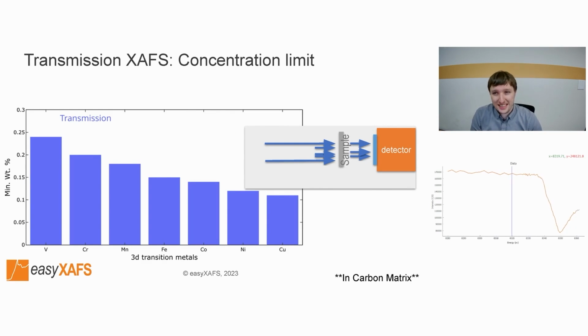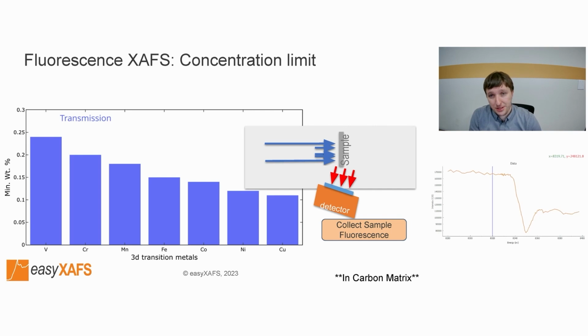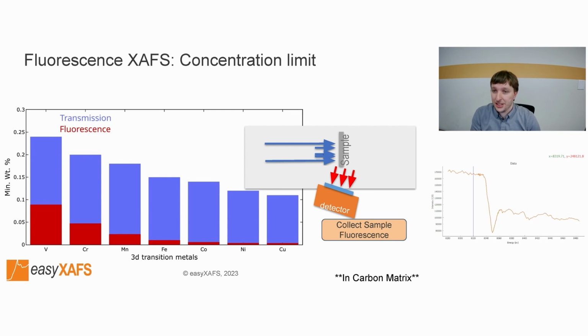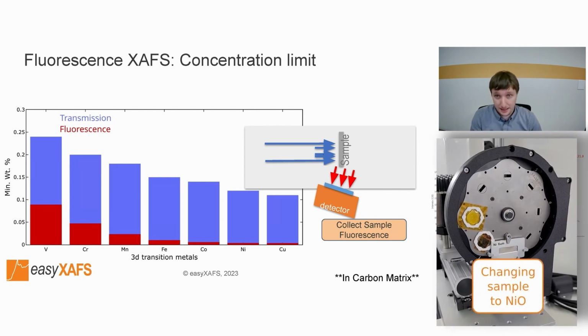While in some cases, sub-weight percent measurements are possible, typical sample concentrations are in the order of 1 to 5% for transmission mode to achieve reliable data. However, it is well known that fluorescence mode is a suitable technique for achieving sensitivity to lower concentrations by directly collecting the elemental fluorescence from the sample at the synchrotron. When we bring this technique into EasyXAFS spectrometers, we found that we could measure and achieve sensitivity all the way to sub 0.1 weight percent for 3D transition metal compounds, and even lower for certain elements.